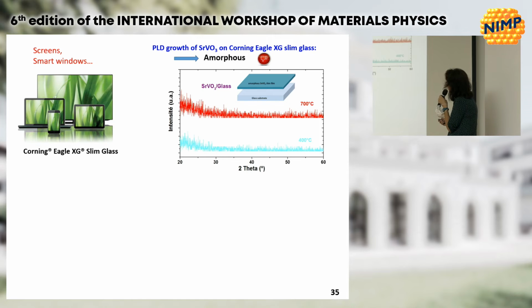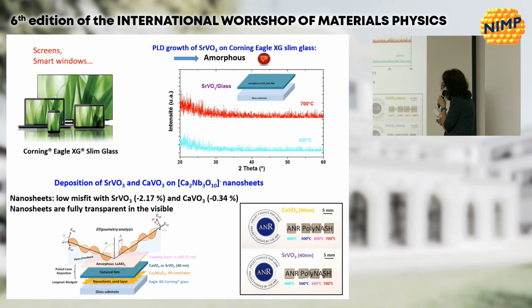We also want to integrate this kind of material on glass, like this Corning Eagle XG slim glass, which is the glass we find in a smartphone or a television. If we grow these oxides on glass at 400 degrees, they are amorphous, and even at a higher temperature, at 700 degrees, they are also amorphous. This is really a problem, because amorphous means insulating. This is the motivation to use nanosheets to induce a crystalline growth of these materials.